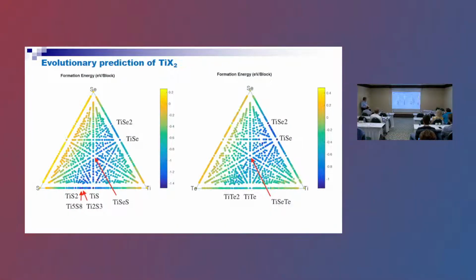So basically, the idea is, I told that we have some ratio of titanium and selenium, and then calculating with this number of atoms all the possible structures, and after that relaxing all these structures. We also calculated some triple states like selenium, titanium, and sulfur, and tellurium. But I will speak about basically titanium diselenide and titanium ditelluride.